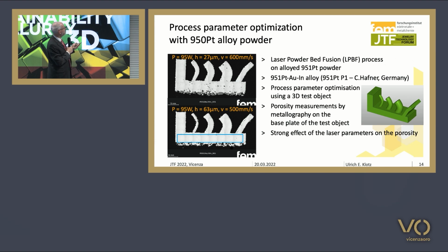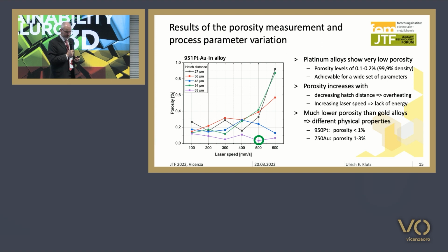You see that depending on the parameters, you can get very different results in terms of porosity. We determined the porosity by looking at this blue area marked here, and we measured the porosity by optical metallography. This is a plot of the porosity as a function of laser parameters.